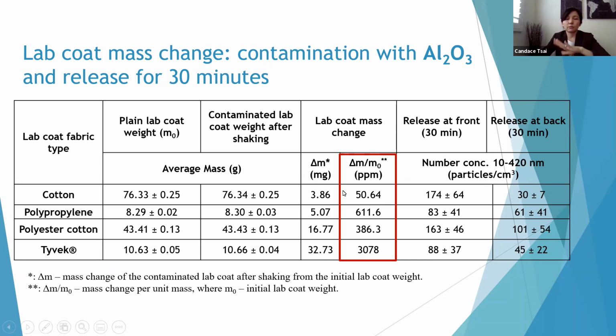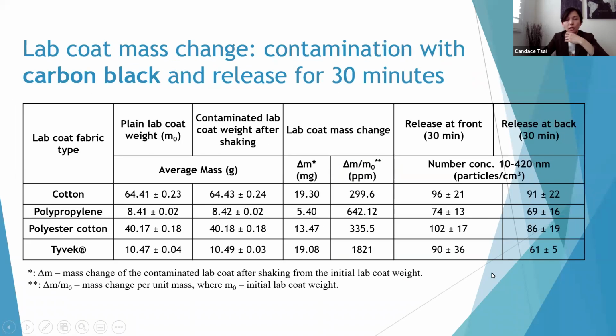So when we analyze per unit mass of the lab coat, we can see that the nanoparticles actually deposit a lot on the Tyvek and polypropylene, even though we didn't see that much coming out - they are quite significant compared to the unit mass of the lab coat.